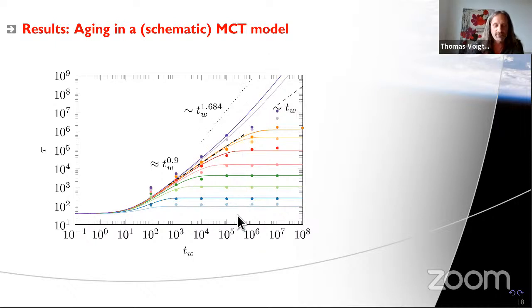So the colored lines are actually a hybrid schematic theory that takes Magdalena's evolution equation for the static structure factor and combines it with the schematic model of mode coupling theory, because that's something that the mode coupling community has always been strong in saying, oh, we are too lazy to solve the full equations, so we make schematic models of which we make sure that they recover the same asymptotic laws, and we can even use them to fit data because we have some free parameters that we can tune. And this is exactly what I did here. So you see, you get a rather nice fit of the simulation data up to a certain point. And then for the two deepest quenches, for the two quenches to the highest state points that you had in the simulations, yeah, there are 4 points that are really falling off this predicted asymptote. And that's, of course, a pity.